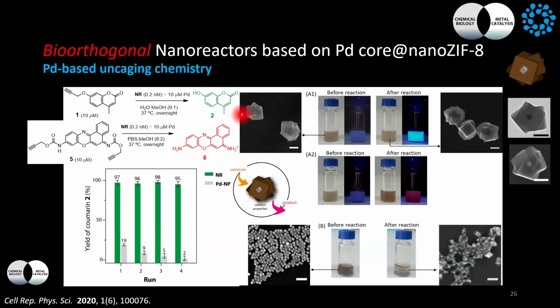In the case of the MOF, here we have in the middle a nanocube of palladium. This is before the reaction. You see that you have little blue, and after the reaction, you have this fluorescent product. And the same with this other reaction. Okay? So Jose Luis, the first thing that he told us to do was to do this in cell lysates, in PBS, and so on, because this kind of reaction works very well in organic solvents, and we wanted to do it in aqueous solvent with cells.